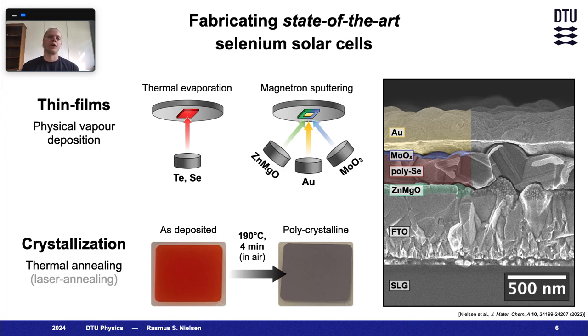In our lab, we fabricate our selenium solar cells using physical vapor deposition techniques. The selenium thin film is synthesized by thermally evaporating an amorphous layer of selenium onto an ultra-thin layer of tellurium followed by an annealing step at 190 degrees centigrade on a hot plate in air to crystallize the deposited film. The purpose of the tellurium layer is just to improve adhesion and uniformity of the selenium thin film. The carrier selective contacts are deposited using magnetron sputtering, and the final result is a photovoltaic device featuring a polycrystalline selenium thin film sandwiched between zinc magnesium oxide and molybdenum oxide, as shown in the cross-sectional SEM on the right.